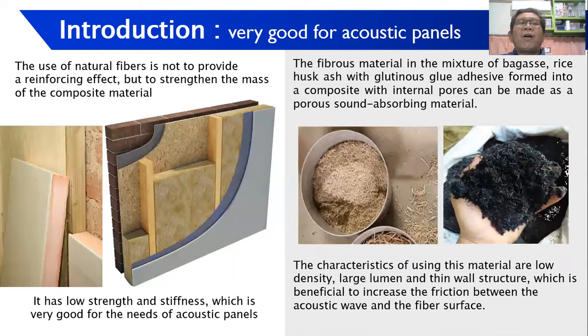The use of natural fiber is not to provide a reinforcing effect, but to strengthen the mass of the composite material. It has low strength and stiffness, which is very good for an acoustic panel. The fibrous material in the mixture of bagasse and rice husk ash with glutinous glue adhesive forms a composite with internal pores that can be made as a sound absorbing material.